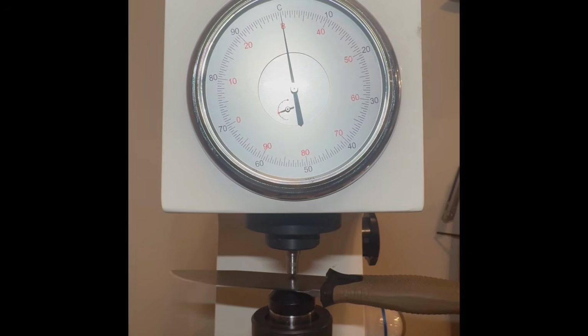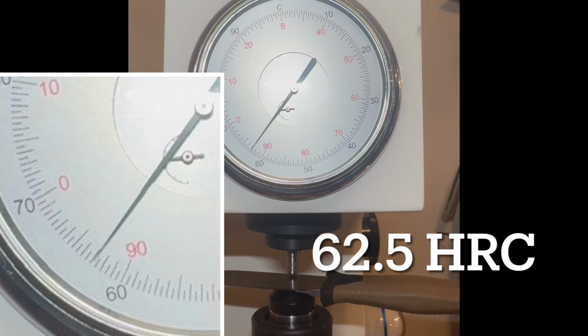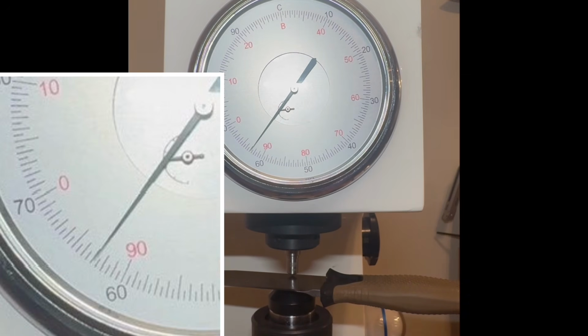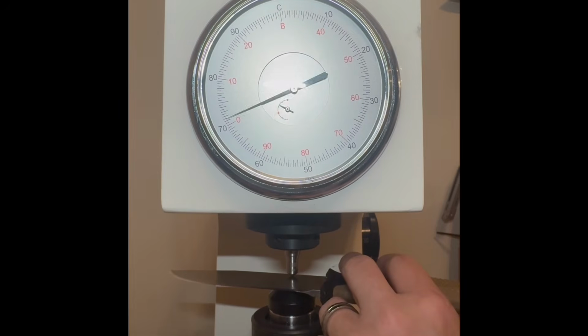So now I'm going through setting up the poke, number one, for the Strongarm. And for some reason our parakeets are going wild in the background. I apologize for that. And then the descent of the weight takes 10 seconds. That's why there's a pause here. I will cut it out in the consequent tests. The first result is 62.5 HRC after minus 0.4 HRC correction. Setting up the second shot.